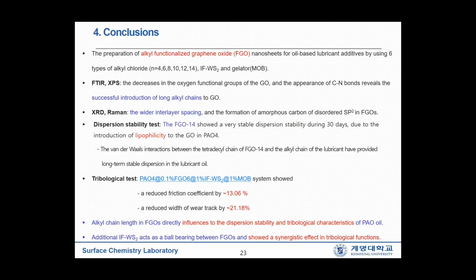By the dispersion stability test, FGO14 showed a very stable dispersion stability during 30 days due to the introduction of lipophilicity to the graphene oxide in PAO4 base oil. And the van der Waals interactions between the tetradecyl chain of FGO14 and the alkyl chain of the lubricant have provided long-term stable dispersion in the lubricating oil.